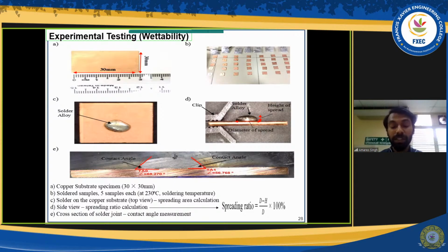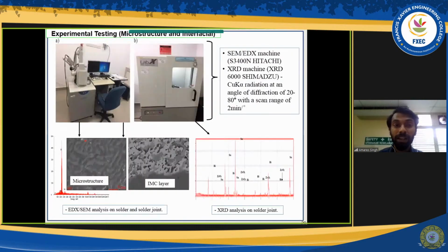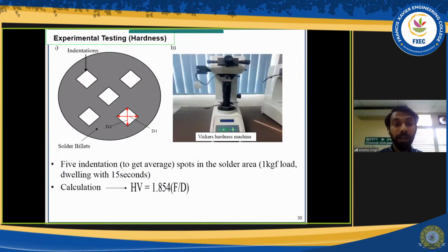We have a special microscope that is embedded with software that I can use to measure the contact angle, and I also have to calculate the spreading area and spreading ratio. Of course, the microstructure involves SEM and EDX together with XRD. These are to detect whether the nanoparticles are present in the structure, and at the same time what is happening at the intermetallic layer. So I can see what happens when the nanoparticles are added and what happens when there are no additions. For hardness, I'll be using Vickers hardness because alloys are considered soft metals, so I can't be using the higher hardness machine. Vickers hardness is the recommended. So I've imposed a 1 kilogram force load for 15 seconds to get the hardness.